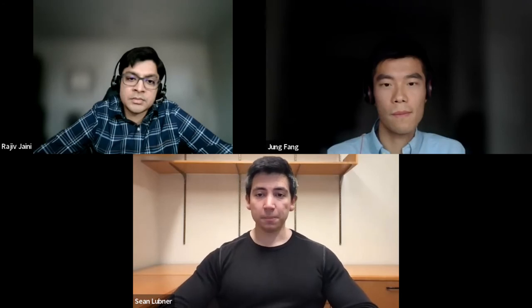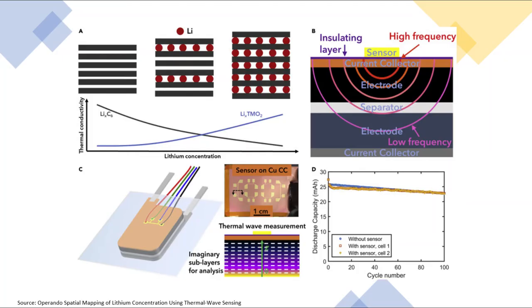We've also then since found that the same technique can be applied, as I mentioned earlier, to look at other properties in the battery. So for example, we have found that you can measure the distribution of lithium concentration within a single layer, in this case, the anode, so 70 microns thick. And you can look at how that changes as you're charging the battery. So you can look at gradients form in your lithium concentration.